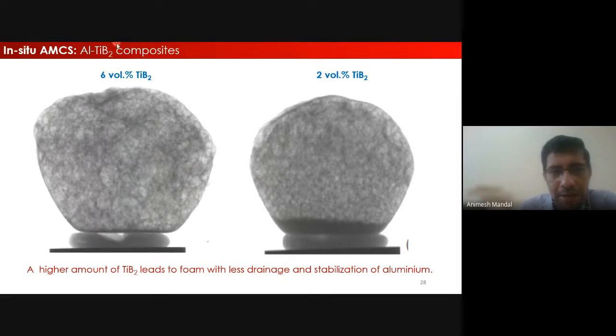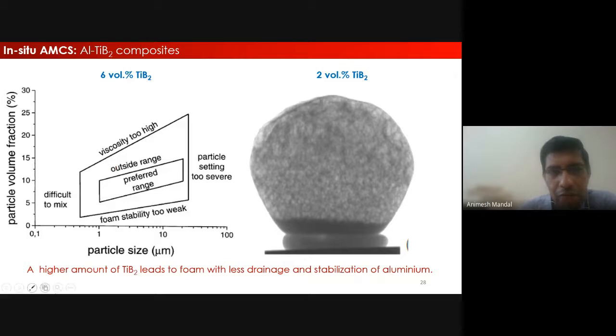Though here I'm showing the example of titanium diboride, you can choose any reinforcement for that matter, but again that has to be optimized depending on the size and the volume fraction. You can see here 6 volume fraction TiB2 is able to give a very nice stable foam. Whereas if you have a lower amount of this reinforcement, you can see a dark shaded area at the bottom of this foam. Here what we call this is drainage of the liquid. That means this foam is not stable, and as a result drainage of liquid is taking place, and this has something to do with the amount of titanium diboride present. So you need a higher or an optimized amount of this particular reinforcement so that you can create a stable foam. So that's another application of composites.